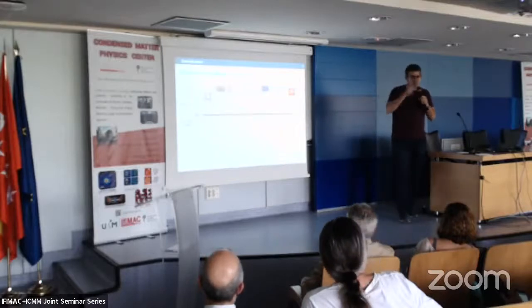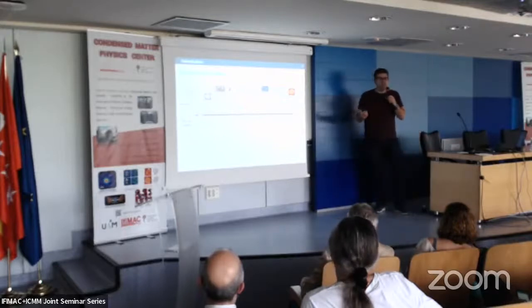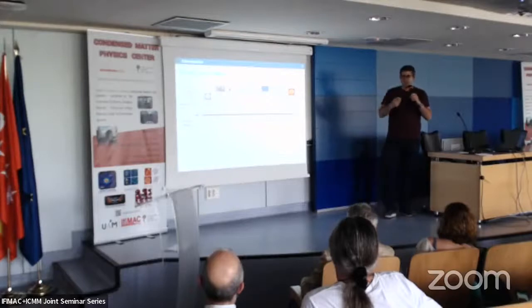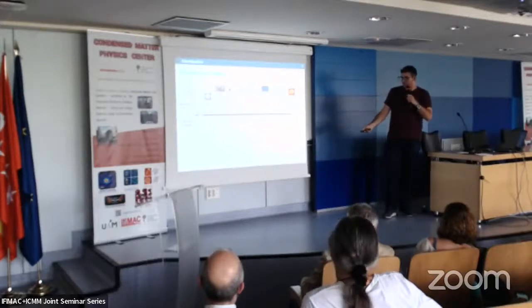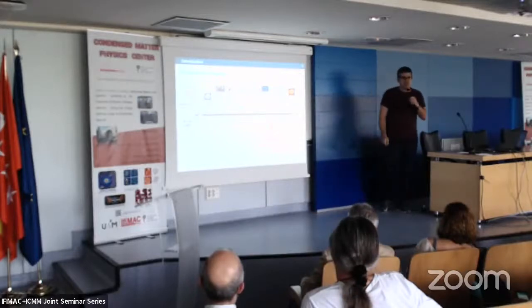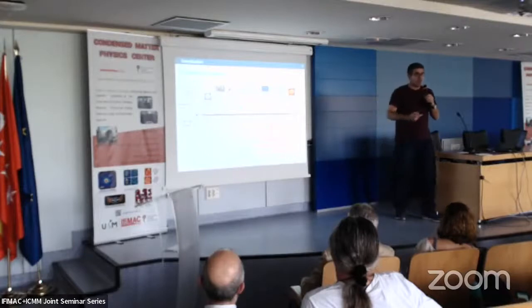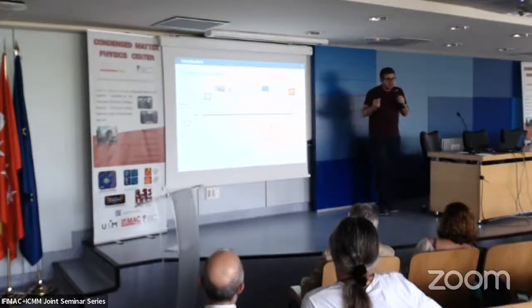And now, if we go back to these pressure ranges, what is the maximum pressure we can achieve with this approach? By just taking into account a standard commercial AFM and standard commercial probes with diamond tips, we can estimate that we can achieve pressures of the order of 300 gigapascals, which is really close to the highest pressure in laboratory conditions, but with the added value that we just need an AFM and commercial probes. Nothing very complicated, just simple stuff.